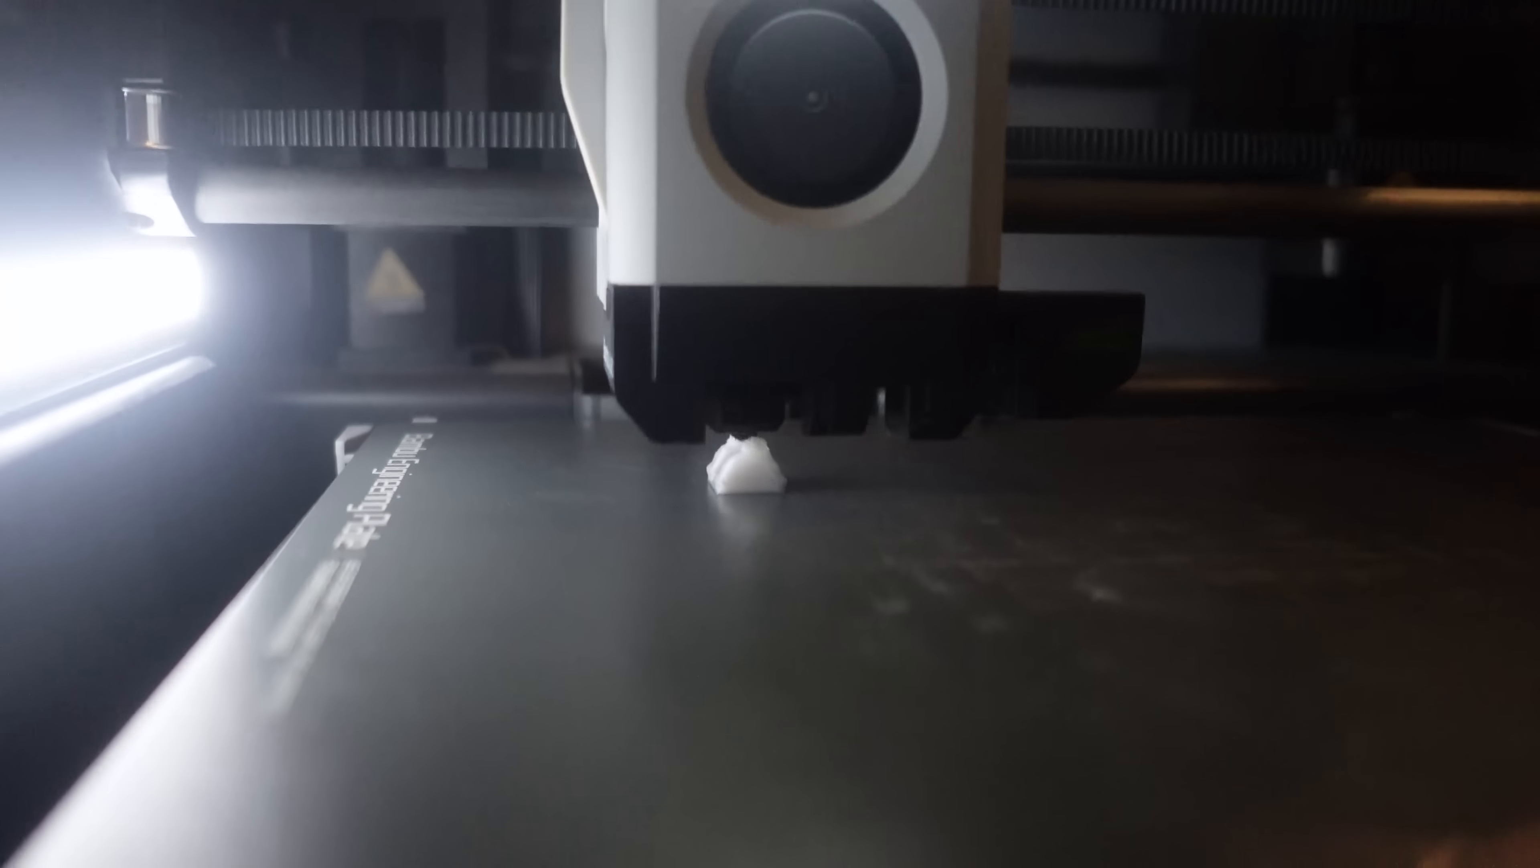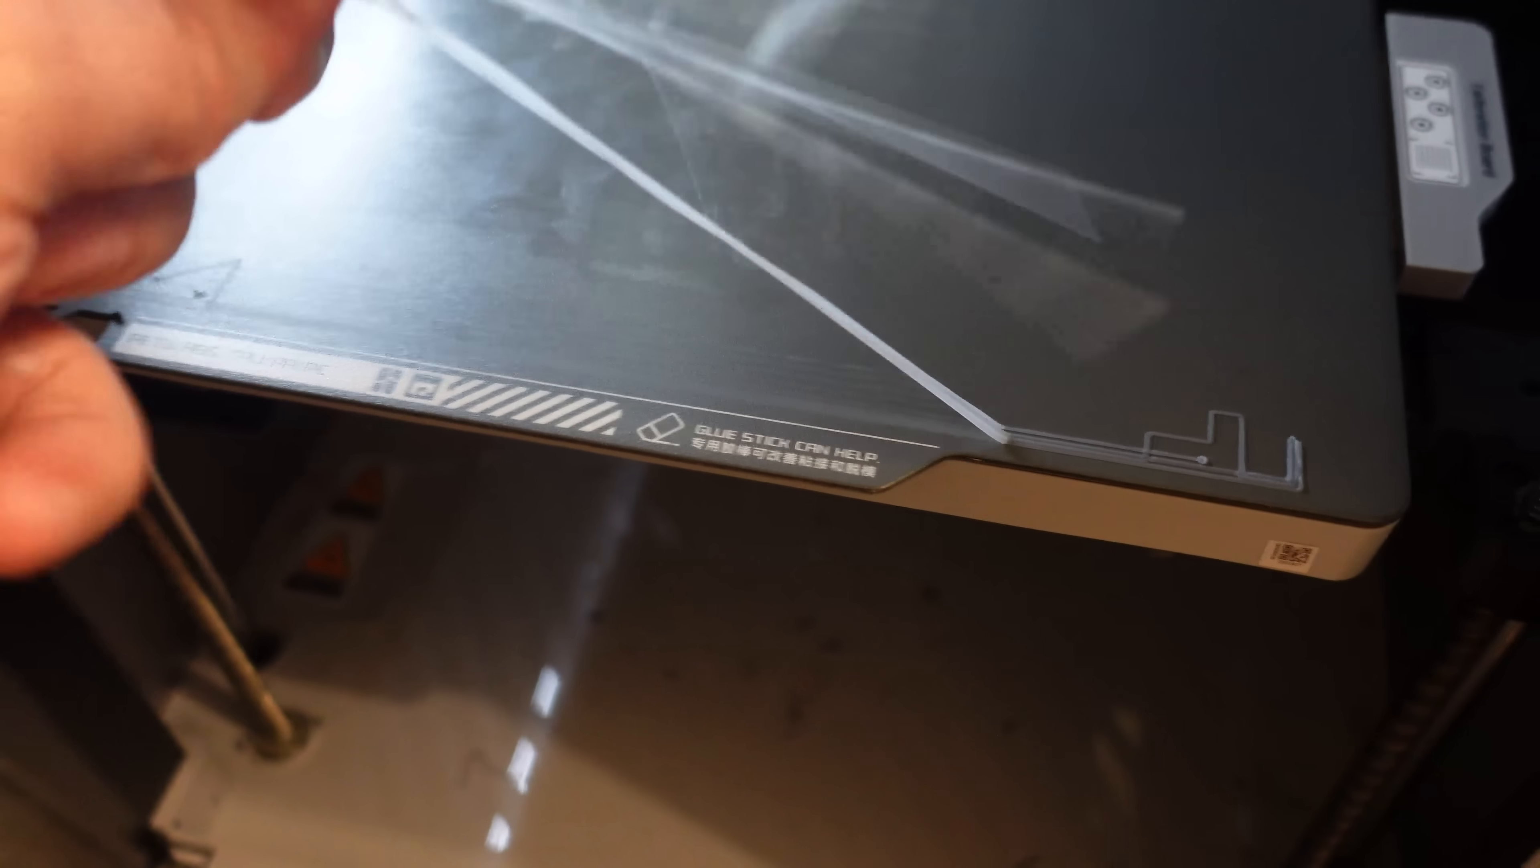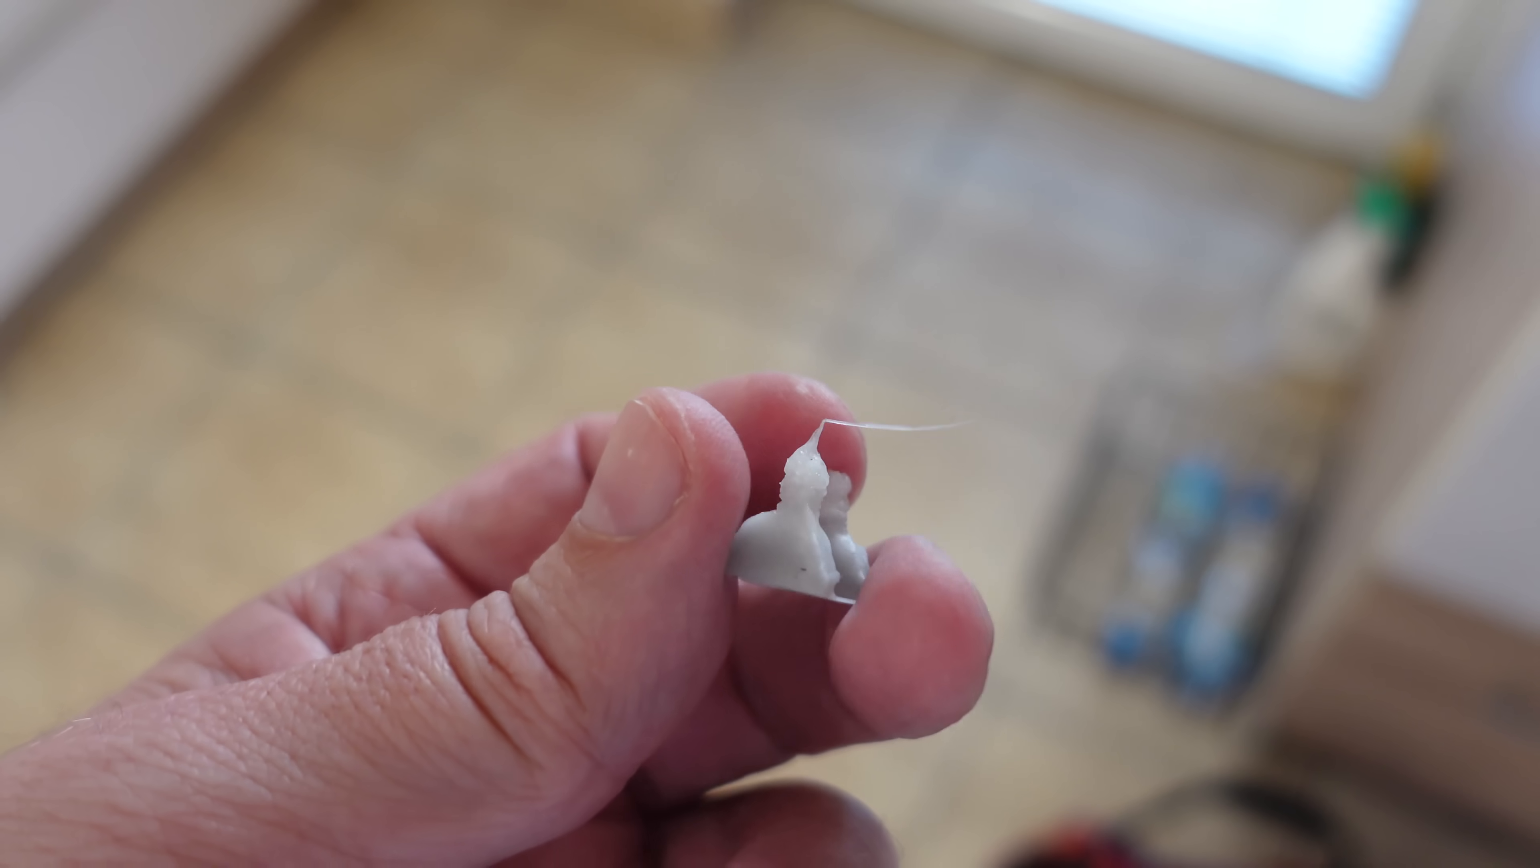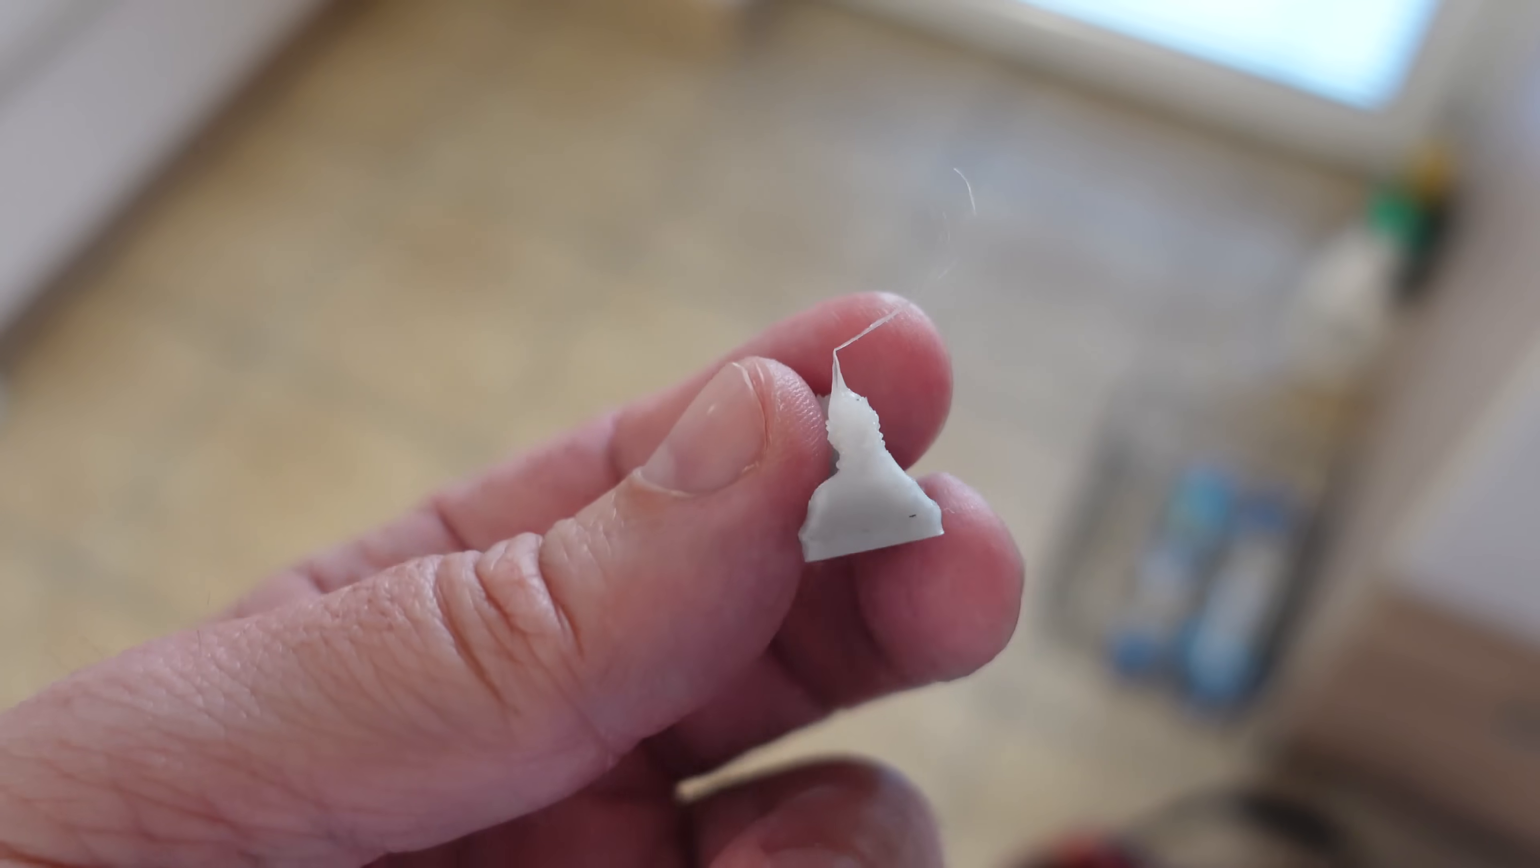Now, I will stop the printing, this part cooling is not enough, it's not solidifying. Even the purge line sticks good, but I have the glue. And thanks to the glue, it is removable, even now. So, the start of the printing is good, the bed adhesion is good too. I have to figure out what is the amount of the part cooling it needs, and don't forget this is printed on 265 degrees Celsius. Imagine this on 290.